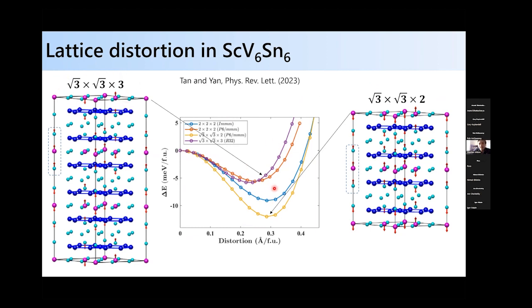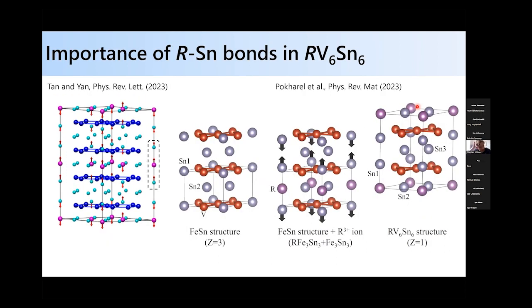You can see it sits in a rather shallow minimum. There are several different types of distortions that may be close in energy, but the DFT-predicted dominant instability is this √3 by √3 by 2. One way of thinking about what's going on is that the primary actors in this lattice instability are the tin and scandium ions.